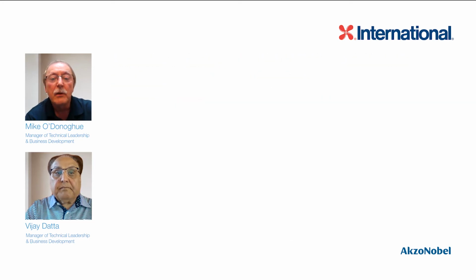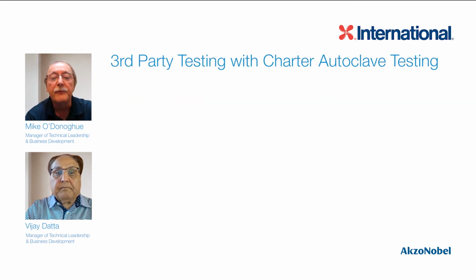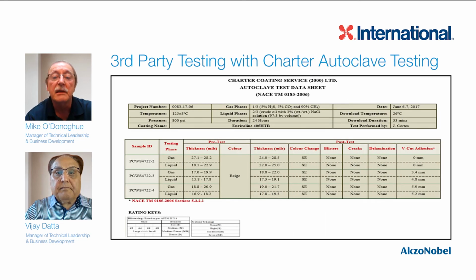Many times, we go to different independent third-party laboratories to test these coatings. Often you'll find that they'll be tested not just at the 5 and 5, the 5% hydrogen sulfide, the 5% CO2, but we'll even go up to say 10, 20, and sometimes even 50%. And these coatings, with 405 HTR being preeminent really amongst them, handle some very high temperatures and large proportions of acid gases.